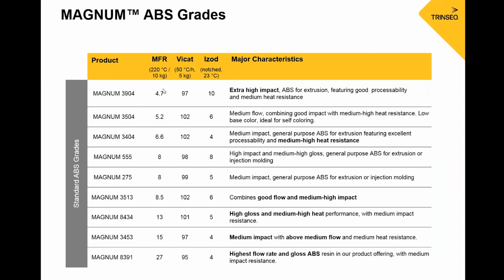The lower melt flow rate is typically what is used in extrusion, like sheet extrusion, and then the higher melt flow rates are typically more prevalent in injection molding for complex mold geometries. So it's very important. We have a wide range of those, and impact as well. Some of the highest impact that you will see with ABS, we have that available with the Magnum 3904, which is also one of the industry leading cold impact resistance values for that product as well.